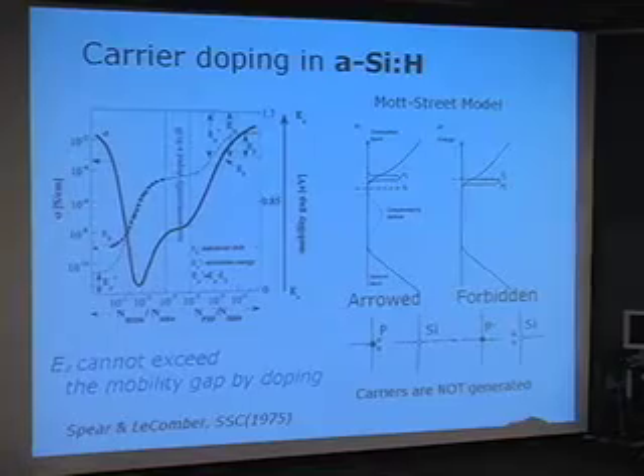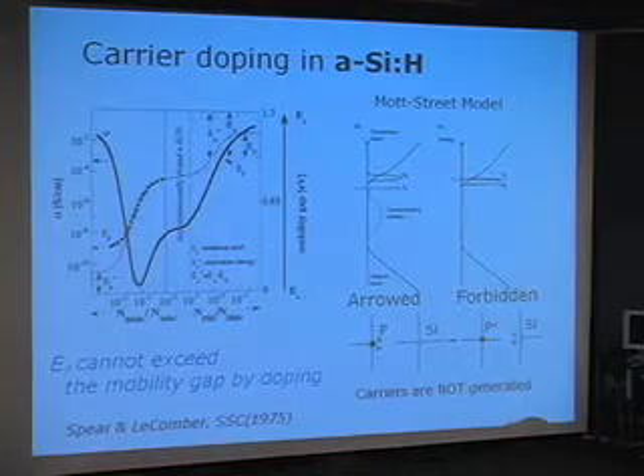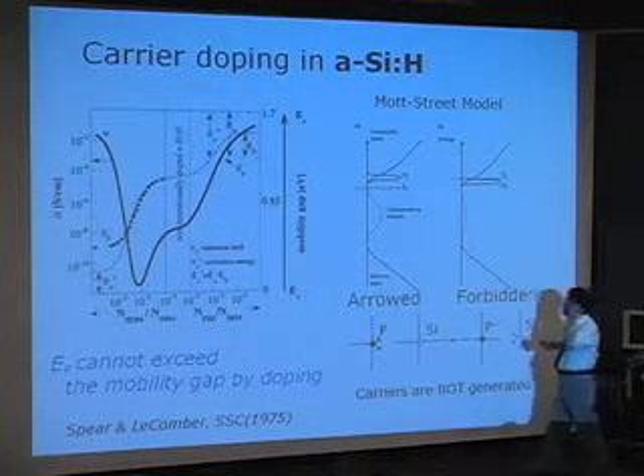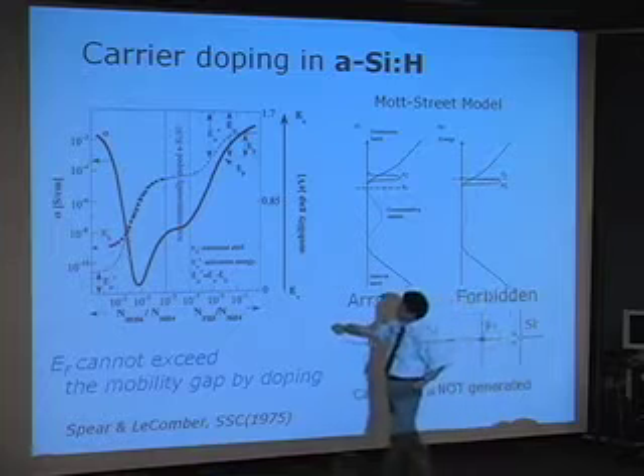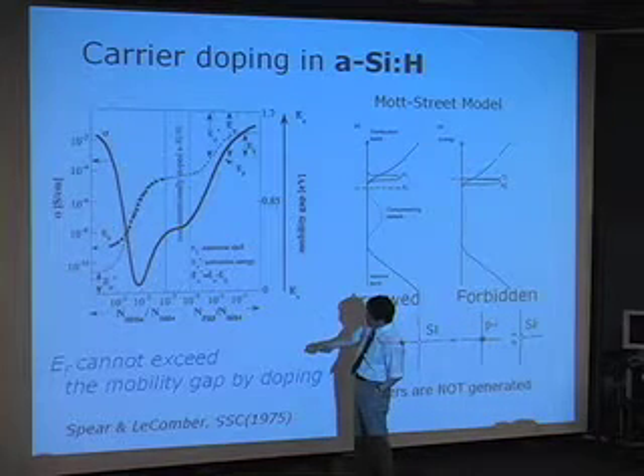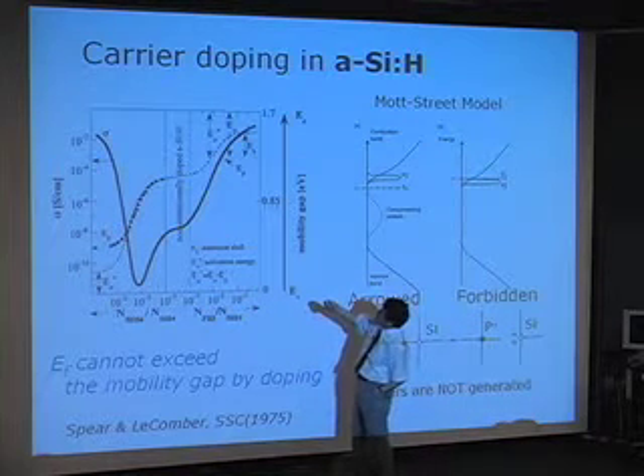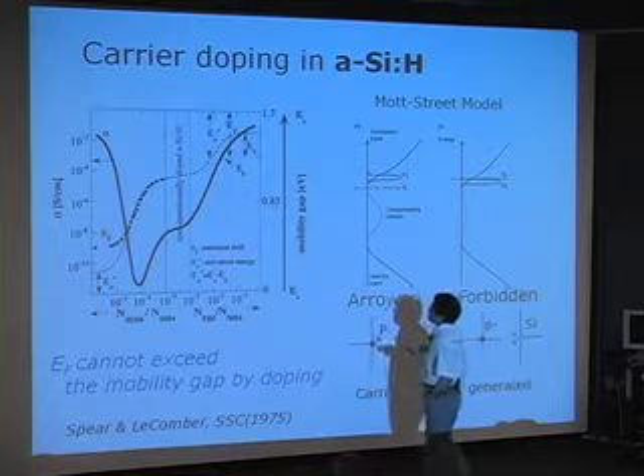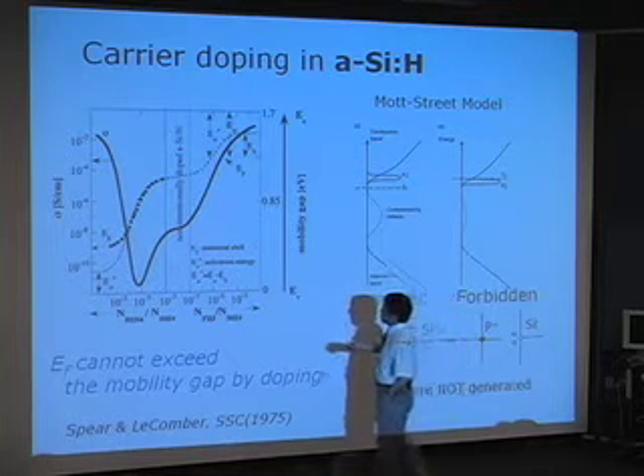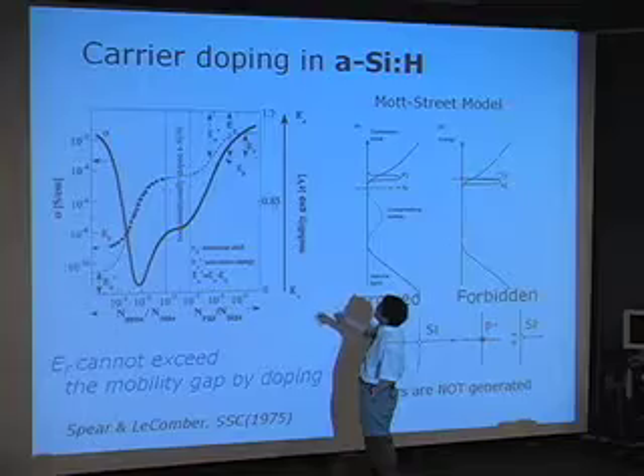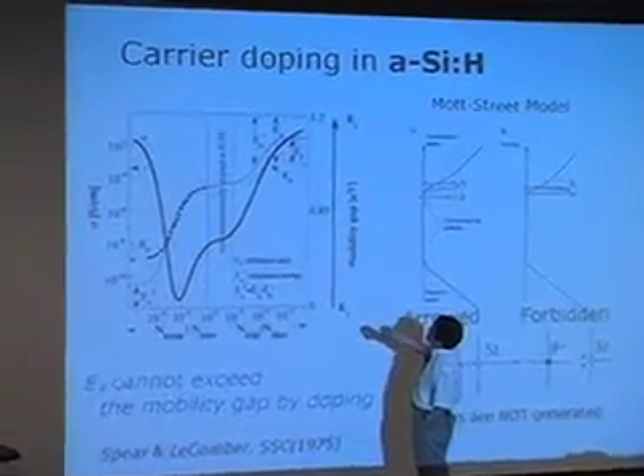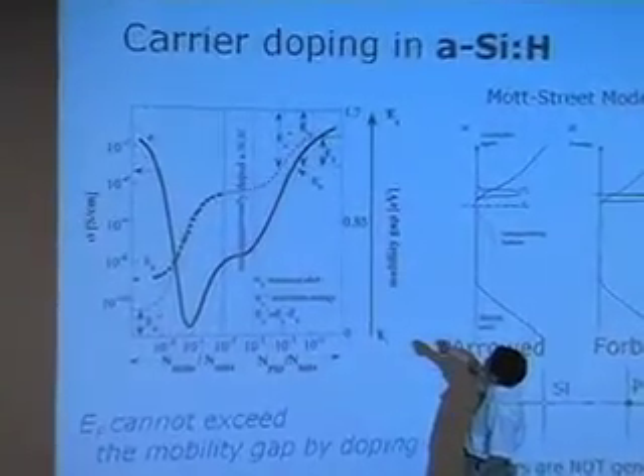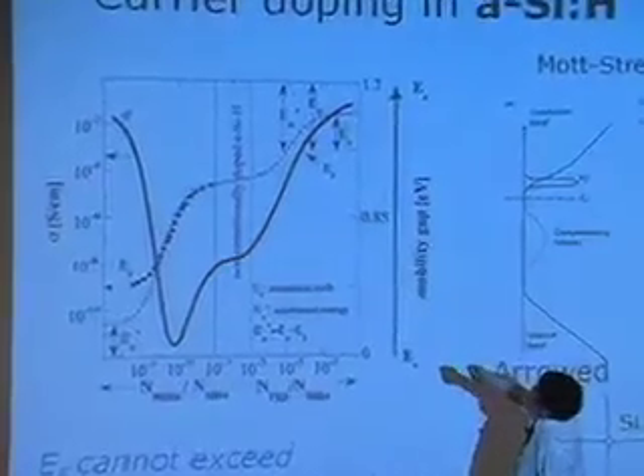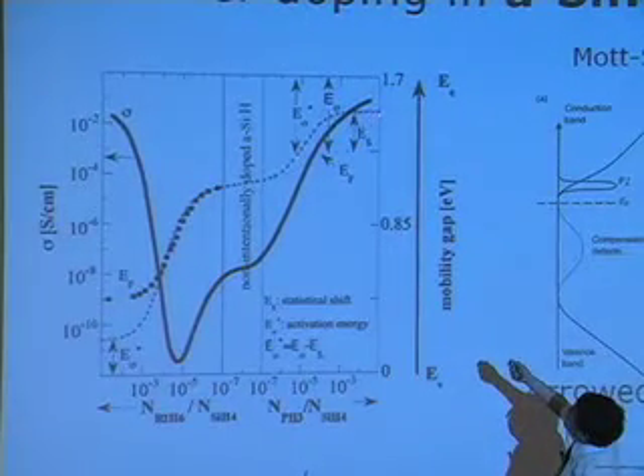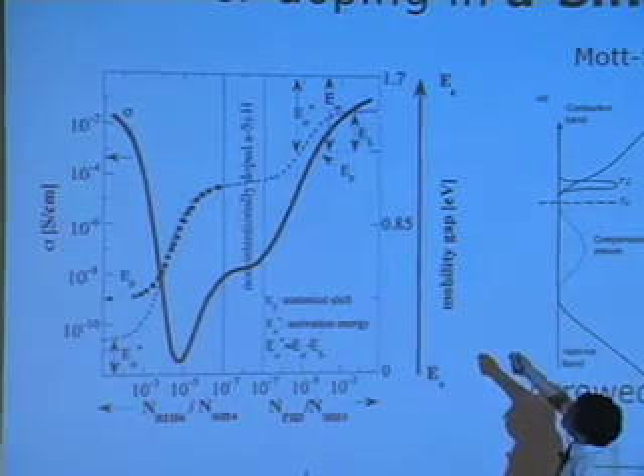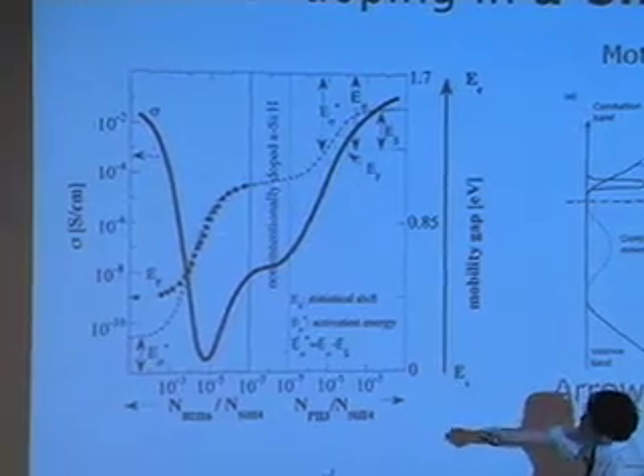Okay, and so this is a comparison with amorphous hydrogenated silicon. This is the data of the amorphous hydrogenated silicon, the famous data by Spear and LeComber in 1975. When the electron is doped, the conductivity is increased, but the Fermi level stops here and doesn't exceed this level. And hole doping is almost the same.